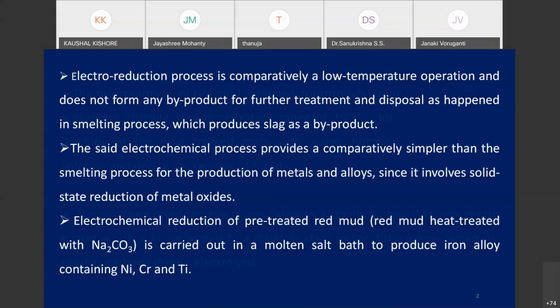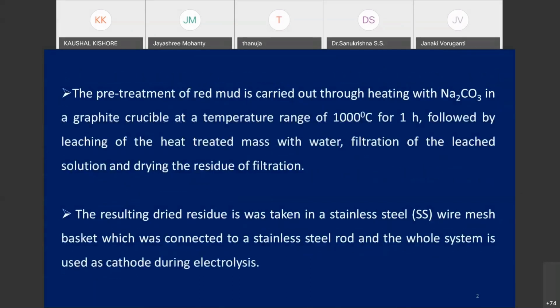Now I am showing you how the pre-treatment is carried out. The pre-treatment is carried out by heating the red mud with sodium carbonate in a graphite crucible at a temperature of 1000 degrees centigrade for 1 hour. So first you carry out the heat treatment of red mud with sodium carbonate, and then you leach the heat treated material with water for removing some soluble material from the red mud.